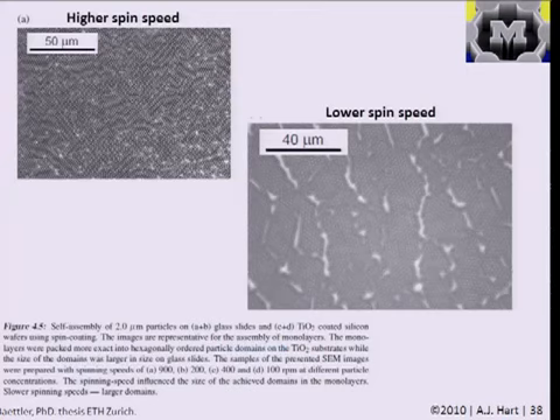So here's a case of depositing these polymer particles on flat surfaces. In this case, we're looking at 2-micron diameter polymer particles on glass slides, just regular glass microscope slides. And these were deposited by the method of spin coating, by taking a droplet and putting it on a spinning surface and spinning it up and letting the liquid fly to the outsides. And these are just 2 data points, but here we see the kind of effect of the spin speed, or the rate of the meniscus motion, on the degree of packing in this layer.